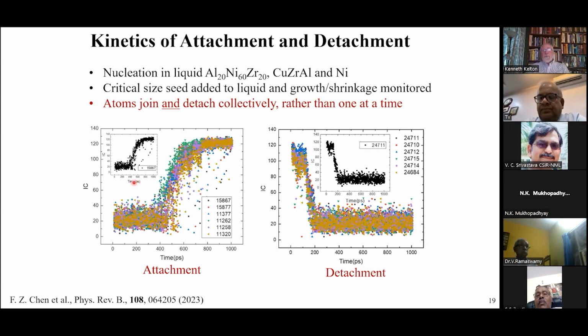It's MD, so these are in picoseconds. And you can see the crystallinity of this particular atom; these numbers represent different atoms. It stays for a while in the liquid phase, and then it decides it's going to join the cluster, and it does so here. So it quickly increases its index of crystallinity to match that of the crystal phase.